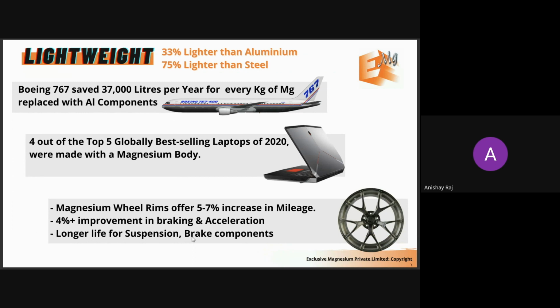So even the strength difference with steel and titanium that magnesium has can be compensated with a slight increase in thickness of the wall, right? Like I was mentioning, the cricket helmet, we had to increase the wall thickness, the diameter of the grill from 2 mm to 3 mm, and that was sufficient to maintain the strength, right? So it is not significant, and with that increase in thickness also, you can achieve a significant weight saving. In the cricket helmet case, we saved about 50% lighter than what was possible with steel, even after the thickness increase.